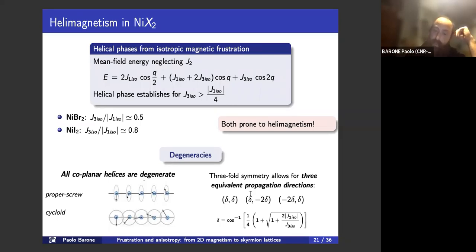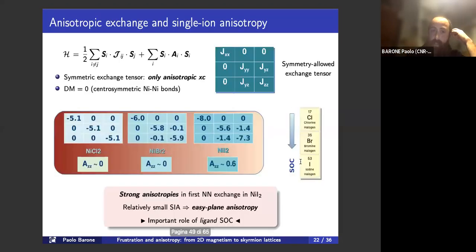There is another class of degeneracy, which comes from the discrete threefold symmetry of the triangular lattice, and that implies that we have three equivalent propagation directions for these spirals. But we still have to go further and introduce anisotropic terms in the system.